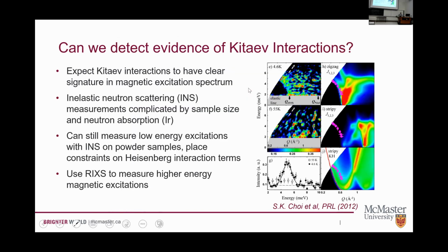All right. So the last thing that I said we wanted to check is if we could see evidence of these Kitaev interactions. Normally, the way we would do this is we would do inelastic neutron scattering, sort of the gold standard for trying to map out the terms in a Hamiltonian. But that's not really an option for us with these materials because they are heavily neutron absorbing and they tend to grow as very small crystals. So sort of micrograms or milligrams in size as opposed to grams. So we just don't have crystals big enough to do these inelastic neutron measurements.